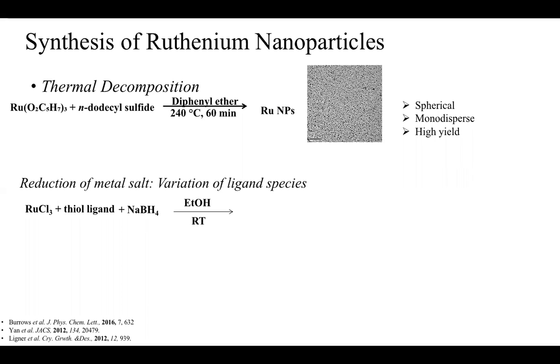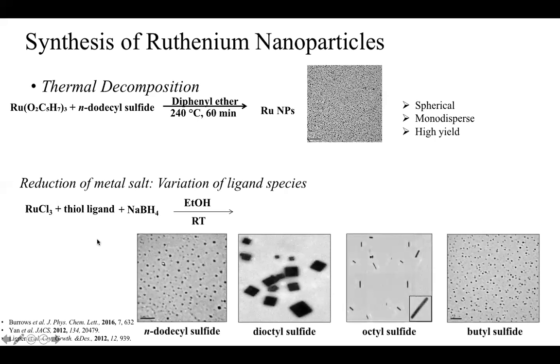So what we did as well is we tried to find out what are different ways that ligand species can help support the growth of these nanoparticles by changing their shapes and sizes. So at room temperature, we also looked at ruthenium chloride in the presence of a thiol ligand and strong reducing agent at room temperature with different size ligand thiol species. And this allowed us to produce different nanoparticles of ruthenium with different shapes and sizes. So ruthenium grows in an HCP growth pattern on its surface. So it is promoted for rods and spheres to be formed. So a lot of times by using those different ligand species, we're able to kind of control the pathway that they grow and the different species that we have based on the chain length.